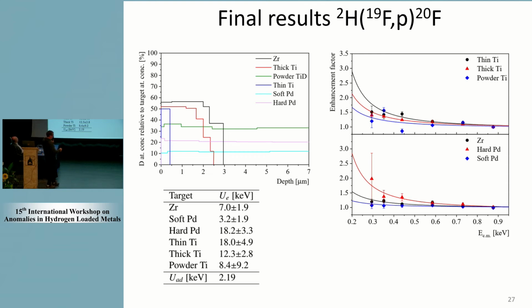Different targets, the same reaction that I was explaining before. We shoot fluorine-19 on deuterium implanted in different targets. We had zirconium, thick titanium, powder titanium, a thin titanium, soft palladium, and hard palladium. And already these are the depth distributions. This tells you something about what happens with deuterium in different targets. In the cases with high diffusion, the deuterium is almost flat, because it's all over the target. But in the cases where we had to implant the deuterium, it doesn't diffuse, so it's only present until a certain depth in the target.